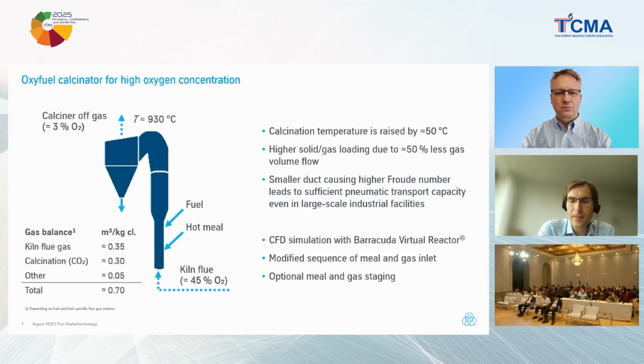In this case, there's a higher solid gas loading due to this less volume flow. On the other hand, we can apply smaller ductwork for this smaller gas flow, which sustains high Froude numbers, which ensure that the material can still be transported pneumatically in the calciner and the preheater. And the lower gas volume flow also notably shifts the capacity flow rate in the preheater, improving the heat exchange between gas and meal and allowing good heat recuperation in the preheater.